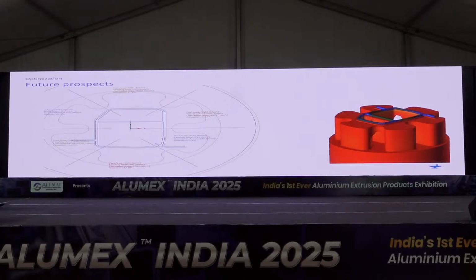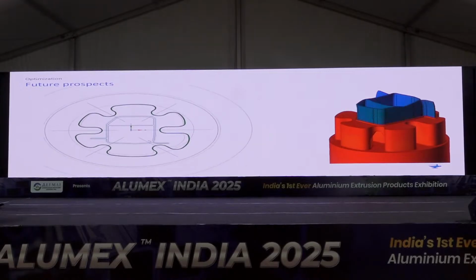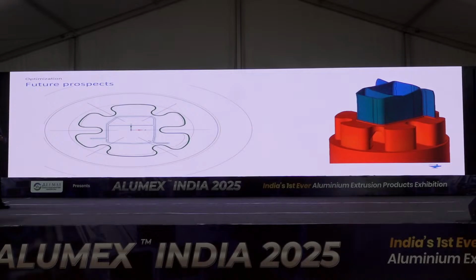So what you can see on the screen is the following. There is a contour of the welding chamber that was produced by a real die producer, and the simulation as well as the real results were great. And the green contour is now provided by the software even before the simulation. So what was done in order to get an almost ideal contour even without the simulation? We analyzed around 150 simulations with box-shaped profiles and, using a machine learning procedure, found an equation that makes it possible to predict a coefficient using the offset contour of the profile to produce the welding chamber. And this is what you can observe on the screen.